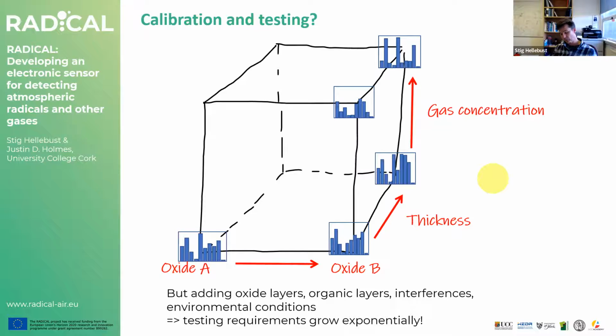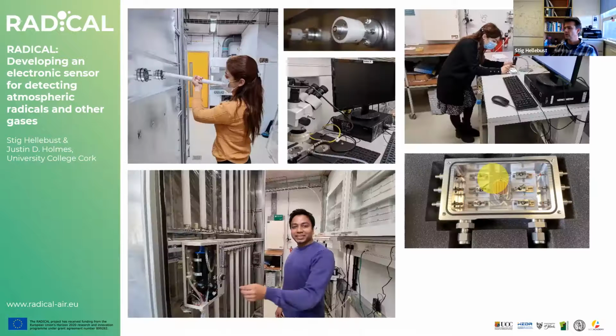So we have to make sure that the experimental design is suitable for use. But the experimental burden falls to Aishali, a PhD student at UCC, and Suba, who is a research fellow on the project, and they have done a lot of testing already. The testing proceeds in four stages. It starts out with this little probe station, which allows you to expose the device to a gas. It's a sealed probe station, so you can control the gas concentration. We have the six cubic meter chamber, where you can have the measurements. This is probably the only atmospheric simulation chamber with the capacity to measure electrical signals from the atmosphere. If there are any other ones, I'd love to hear about them.